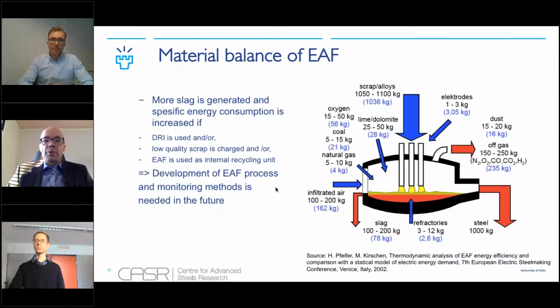If you look at the material balance, we see that if we are producing one ton of steel, we need approximately 1100 kilograms of scrap or alloys. But if we replace scrap by DRI, it means that also more slag is generated, and also specific energy consumption is higher.